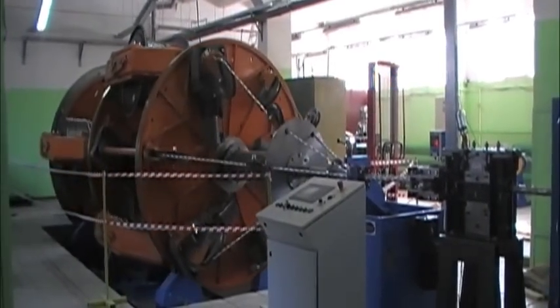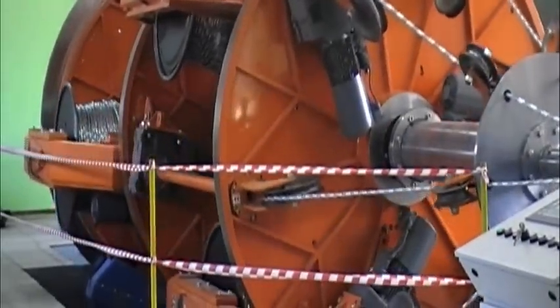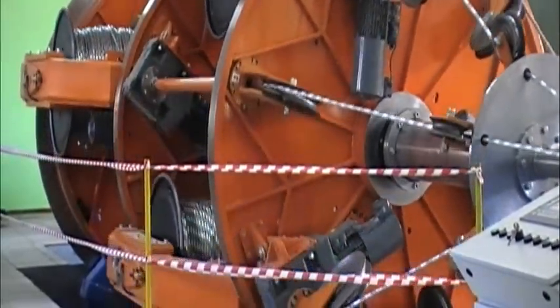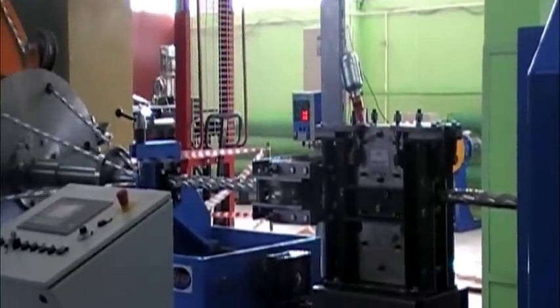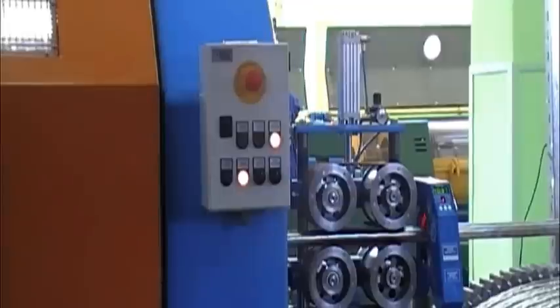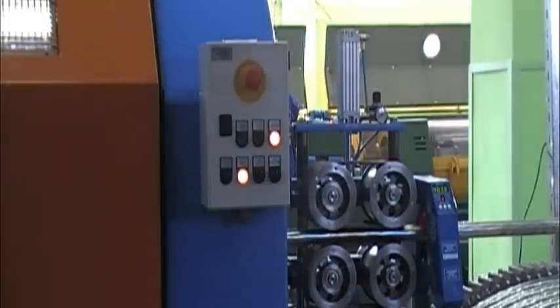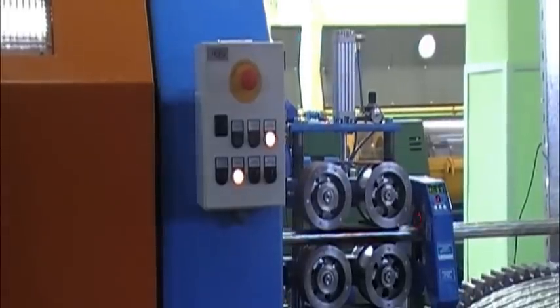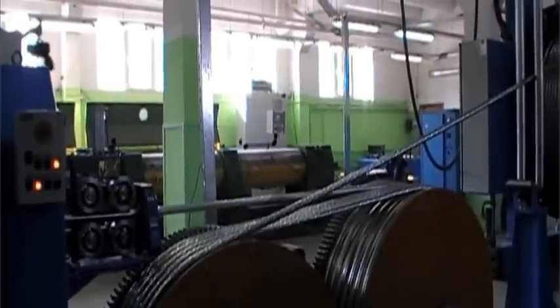This is a winding machine in action. In the picture I showed before, there are 5 lobes, if you will, in this conductor, and this is putting them all together, winding, twisting them together into one cable that comes out of the other end of this machine. Then it goes through this machine, which compacts it. Then it goes on to the right a little farther, through another machine. The stainless steel wrap is put around it, and then we put it on a roll, and that roll is how it's transported to the next place where we'll put a jacket on.